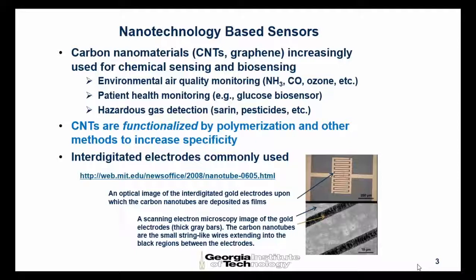So our basic sensing material is single-wall carbon nanotubes, which are functionalized for ozone. This is one of the very innovative sensors, one of the first ones in the field, which came out of MIT in the 2006, 2008 timeframe. Basically, it's a very simple interdigitated pair of electrodes on silicon, but they were able to detect parts per trillion of a hazardous gas, DMMP. DMMP is a precursor to sarin. They used electrophoresis to align the carbon nanotubes perpendicular to these electrodes, and that got excellent sensitivity. So this is one of the very first applications of how nanotubes can be used to design a sensor.